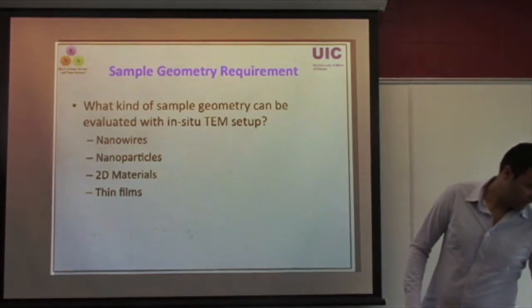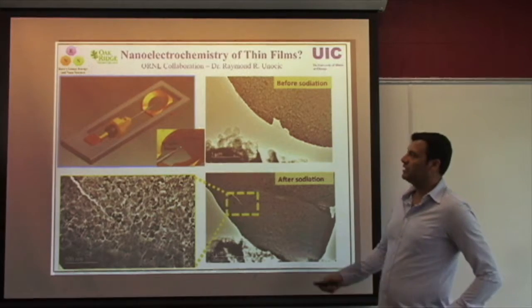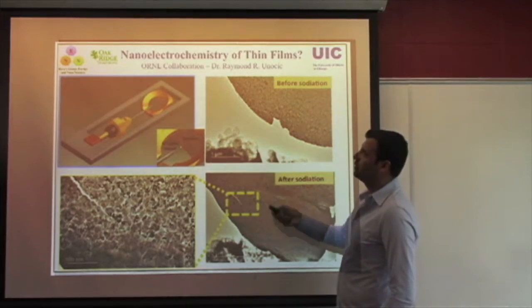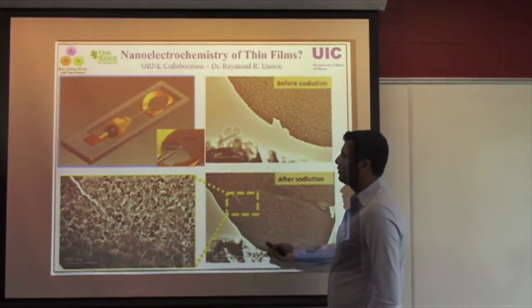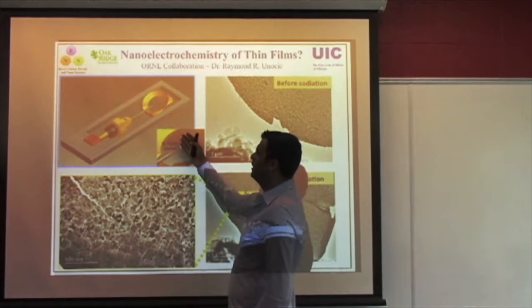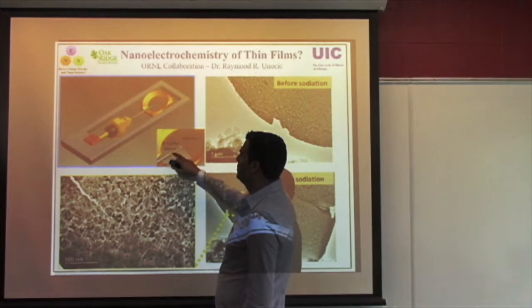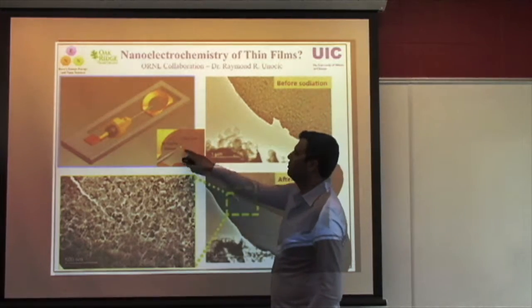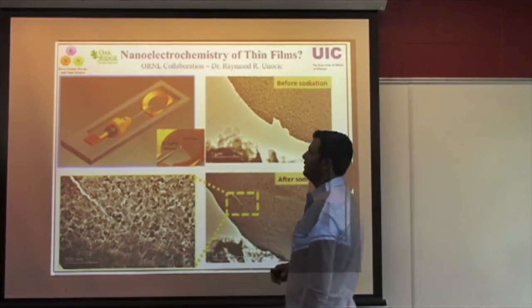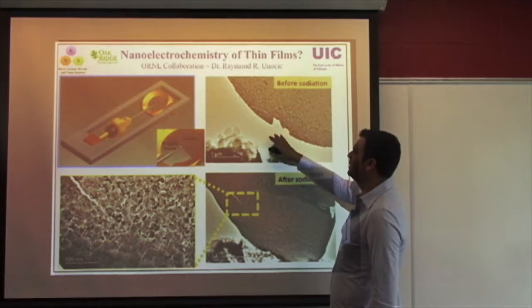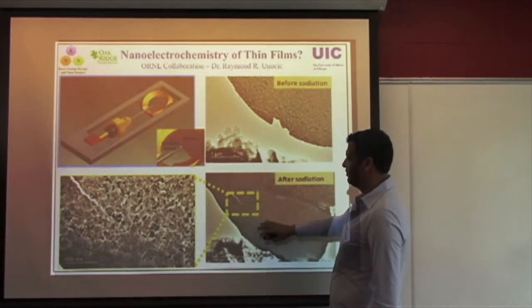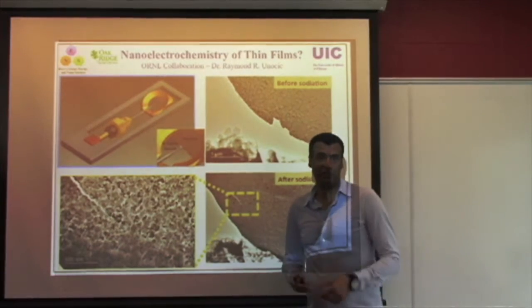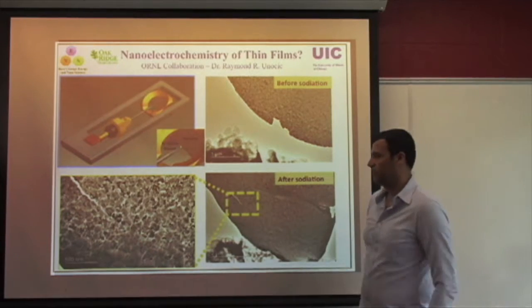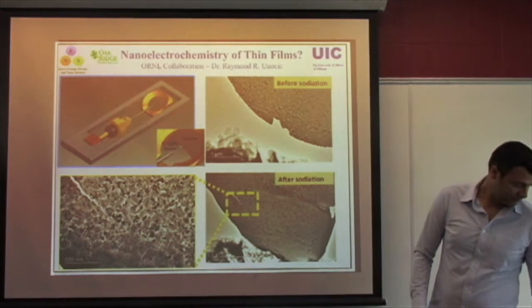This is an example of our collaboration with Oak Ridge National Lab. In this work, we deposited a thin film on a half grid and brought our electrode, which had some sodium as the source. We brought it in contact with our device and system, and then we looked into the progress of the sodiation reaction front into the thin film structure.